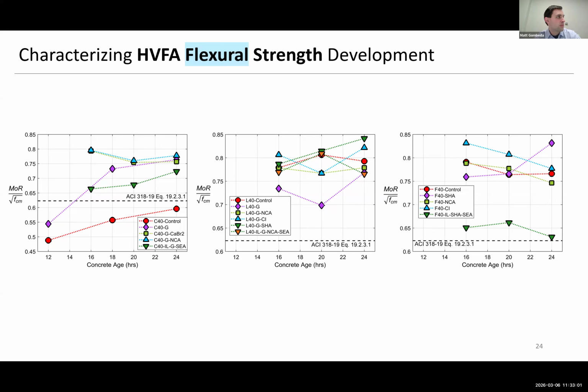Because we were changing the mix design, we have different properties now, but also that equation was largely initially developed at later ages. So we're trying to see how the early age behavior is also characterized in this sense. And we found that most of the time it was conservative, which is safe, but also in terms of dialing in the efficiency of the precast plant, the ability to do flexural testing on your own can help get a better idea of exactly when those performance targets are hit.